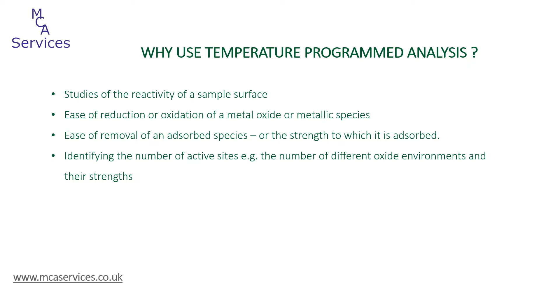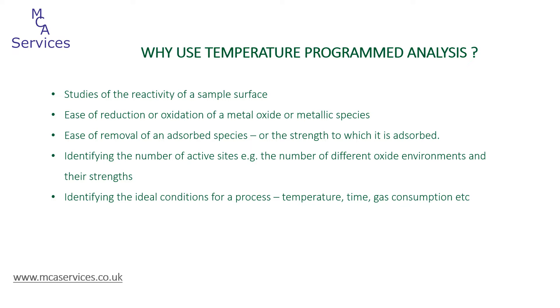We might be interested in identifying the number of active sites and assessing their strength — by this we mean how strongly they form or bond with other materials. From this, we can identify ideal conditions for reduction, oxidation, desorption, or decomposition, such as the optimum temperature, the gas flow rate to use, and the time required for the process to be completed. We can also calculate the volume of gas required to complete the process, and this is called gas consumption.